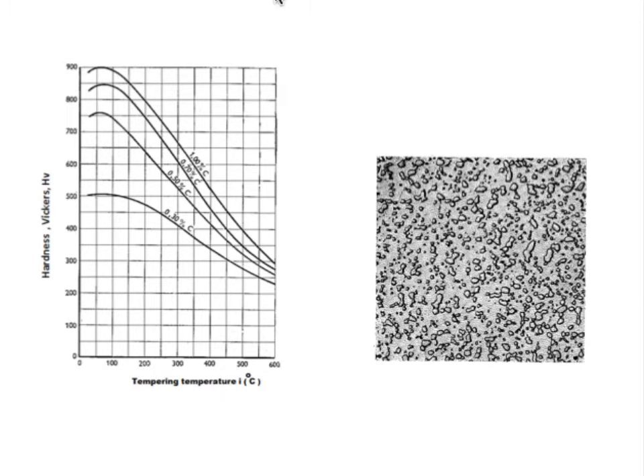Here we now see some tempering curves for some different steels. And what we see here is the hardness on this axis and the tempering temperature here. In this case, the tempering has been going on for 30 minutes at each of these temperatures. And we can also see here the effect of different carbon contents in the steel. This is a low alloyed carbon steel. And this curve is for 0.30% carbon. This is for 0.50, 0.70 and 1% carbon.